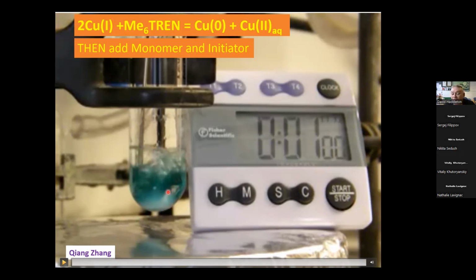And you can do it in the presence of anything, really. So you can do that in the presence of ethanol, in the presence of sugars, in the presence of pretty much any impurity. You don't really have to purify anything. Now, oxygen is quite interesting. So what's happening when we do that, we disproportionate the copper 1 to copper 0. Bearing in mind, we've just made some brand new copper atoms.